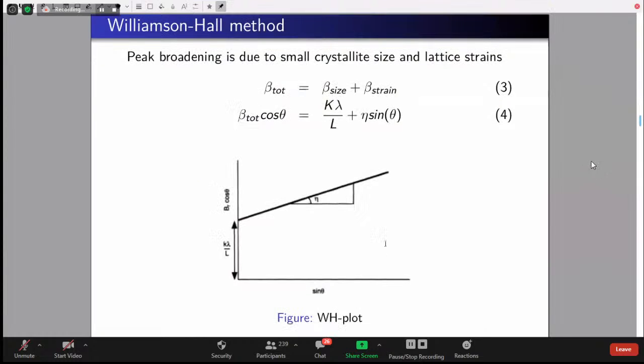The next one is a little bit more sophisticated when compared with Scherrer's formula. We can nicely separate out the contribution of strain and the contribution of crystallite size using the Williamson-Hall method, where we plot beta cos theta against sin theta. Theta is your Bragg angle. The slope is going to give us the amount of strain, and here we will have K lambda over L. Again, K is the constant, lambda is our wavelength, and L is our crystallite size. We can easily calculate and separate out.